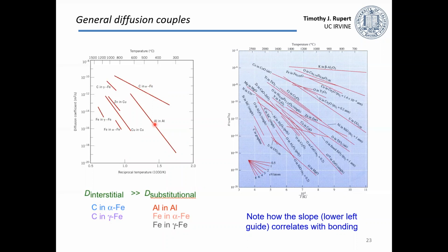And that's actually pretty surprising. Aluminum melts at really low temperatures, so the fact that its diffusivity is lower at the same temperature really shows the effect of an interstitial versus a vacancy mechanism. And those slopes also correlate to that activation energy, remember? The fact that this has a shallower slope means that the activation energy is lower than for this steep slope.